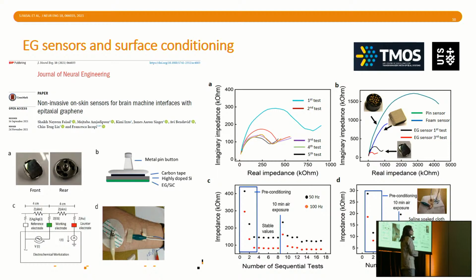But then the second thing that we showed is that you can reduce the impedance. It has to be as low as possible to overcome that problem of reading this microvolts type of signal. That is very important. And we were able to show that by keeping our system in contact with the skin, after just a couple of tests, the impedance would reduce enormously. And actually what we're doing, we understood that later, but I'll show you.